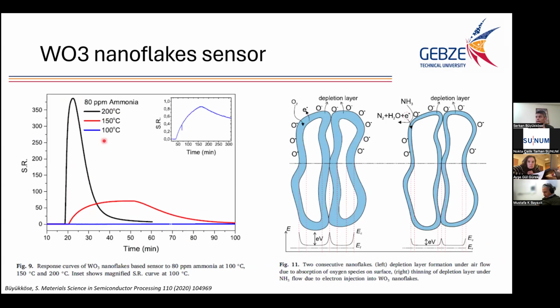Okay, most of the time for semiconductor metal oxide structures, it's quite difficult to get a response at room temperature. You always have to heat up the sensor because you need some activation energy for the reactions. So the best results in our case are obtained at 200 degrees. Actually, even at 100 degrees, we have some response, but it's very, very small.